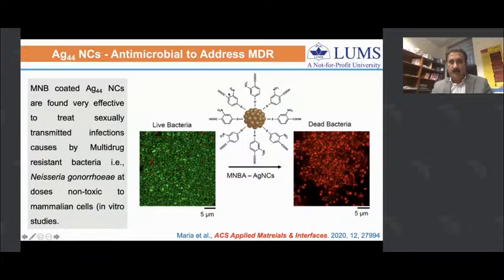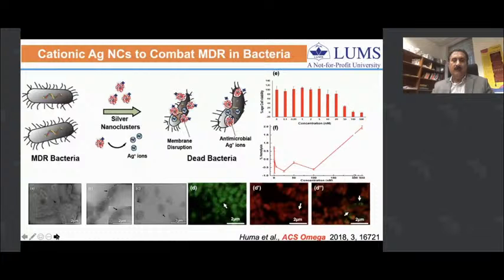Apart from this, if you note carefully, these clusters have a negative charge, but we know that bacteria surface is also negatively charged. So in order to enhance the interaction of these nanoclusters with the bacterial surface, we developed silver nanoclusters coated with cationic polymers like polyethyleneimine.